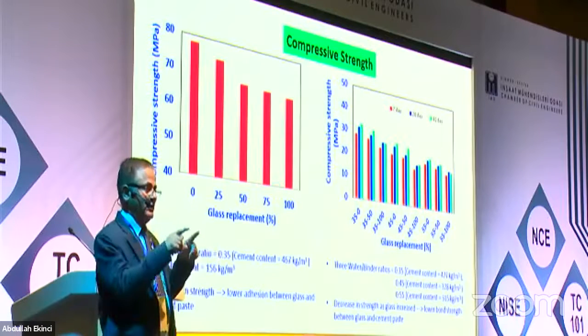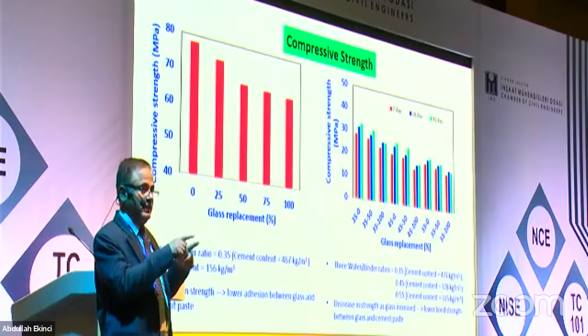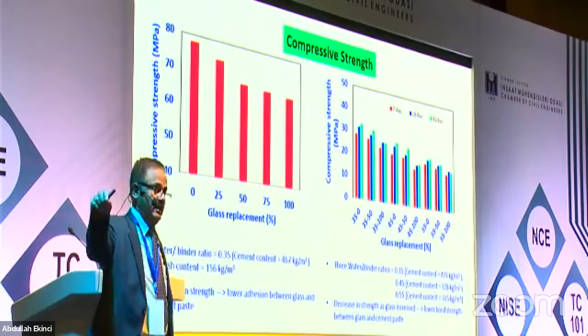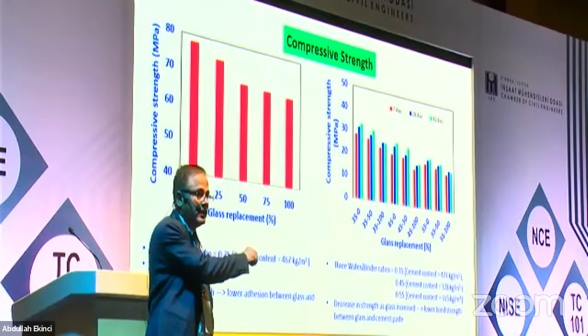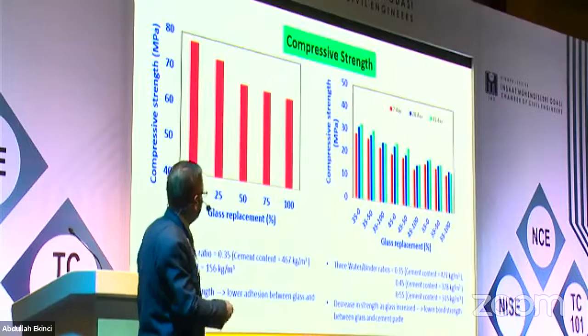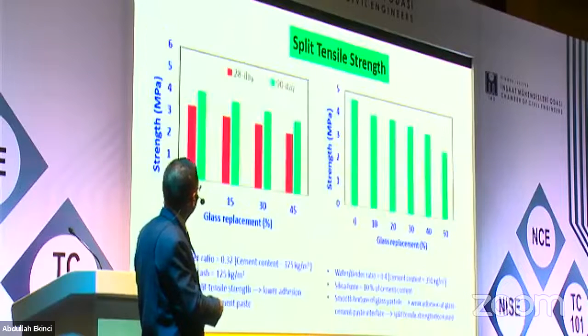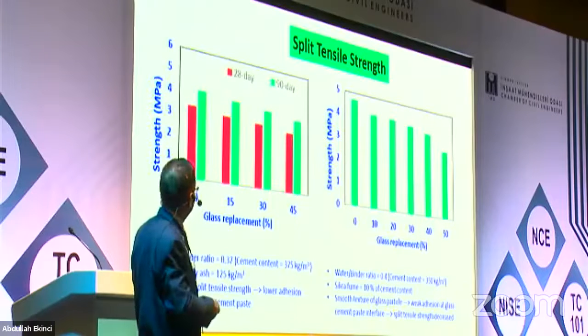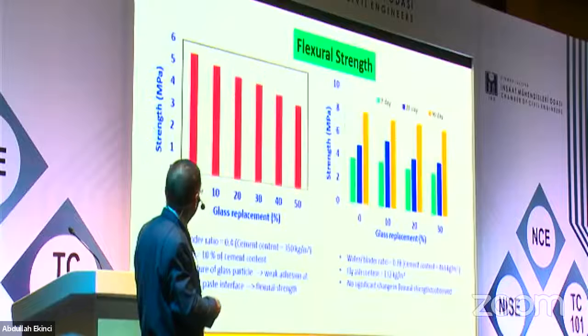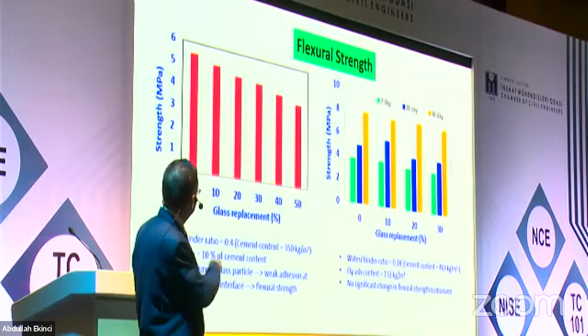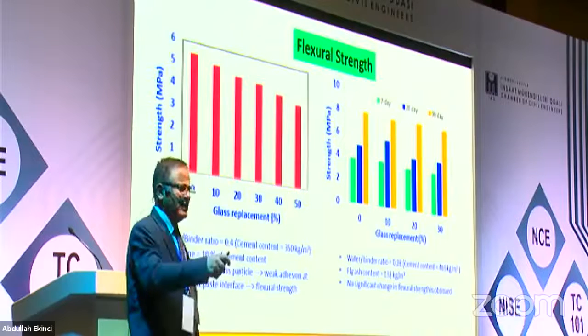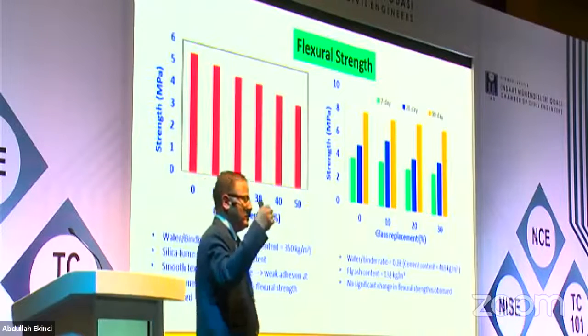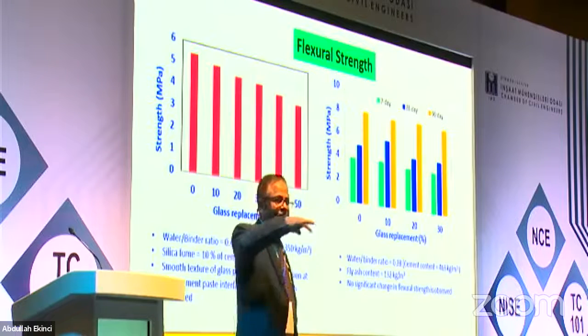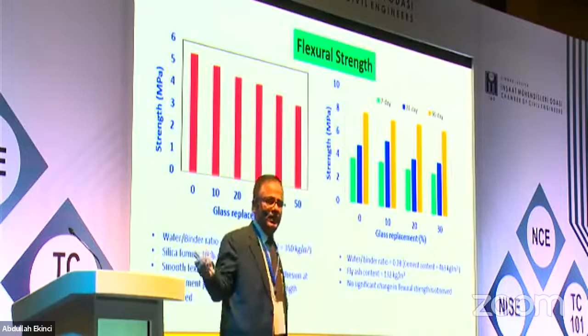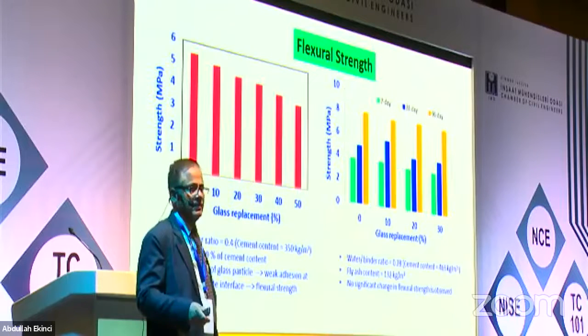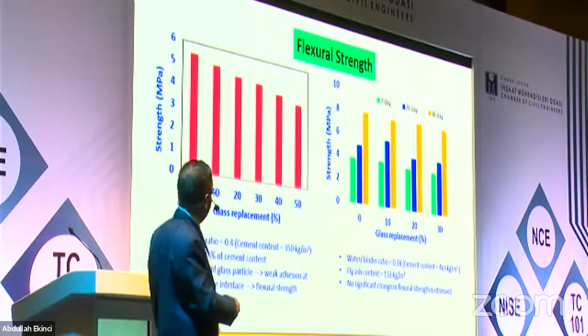But again, this research alone can be misleading. You need to see durability properties, particularly ASR, along with workability. Similarly, split tensile strength results are more or less similar. And coming to flexural strength, the good strength achievement is consistent and is not much decreased compared with the control, whether it is research in Korea, Turkey, or Canada. So compressive strength is not an issue with this material.